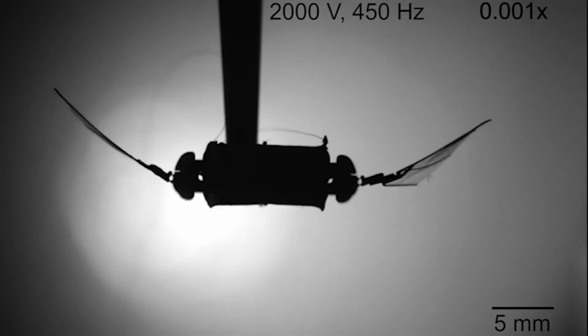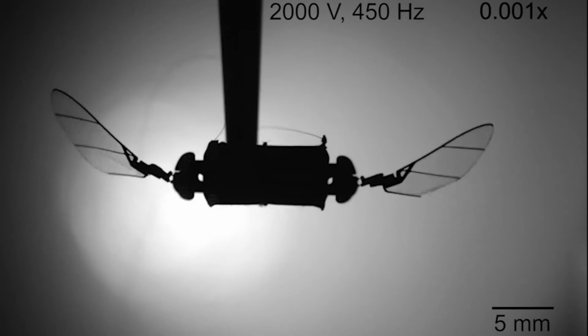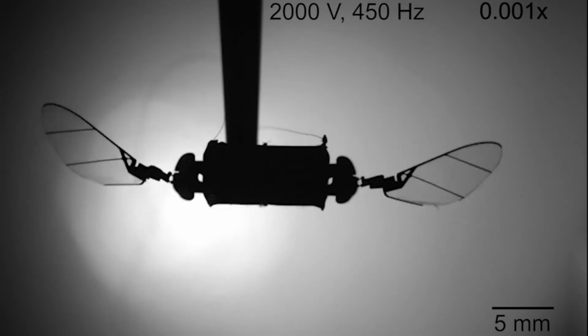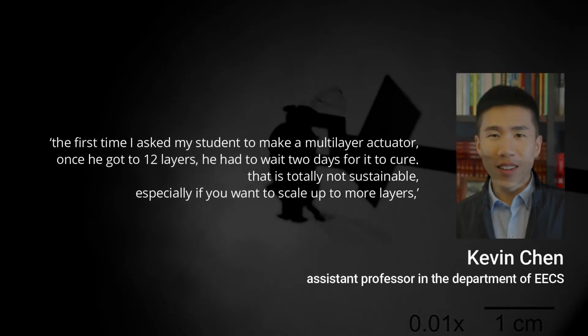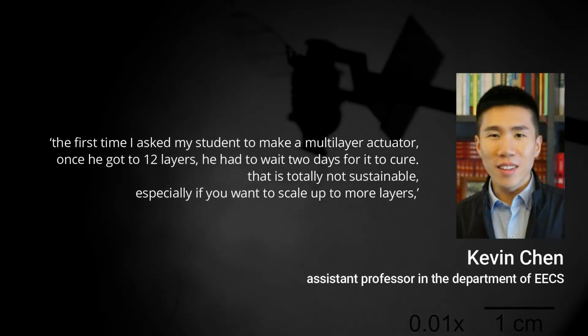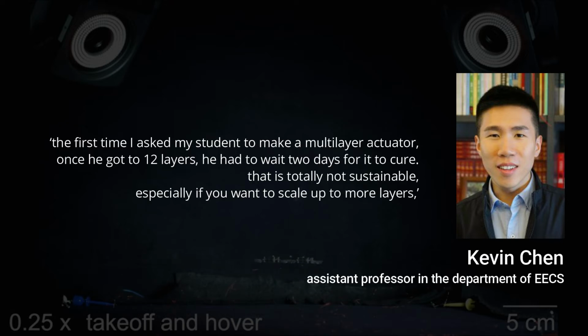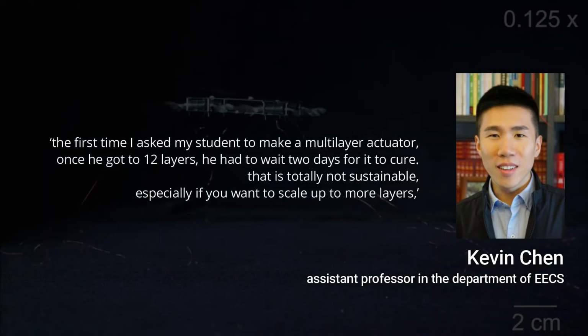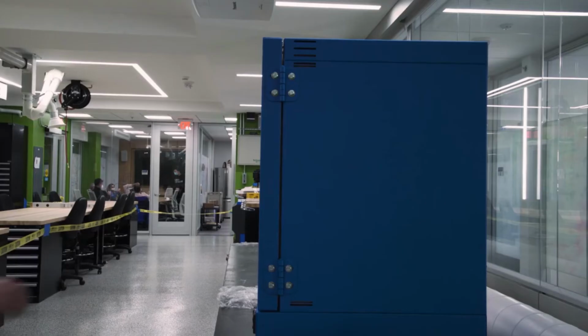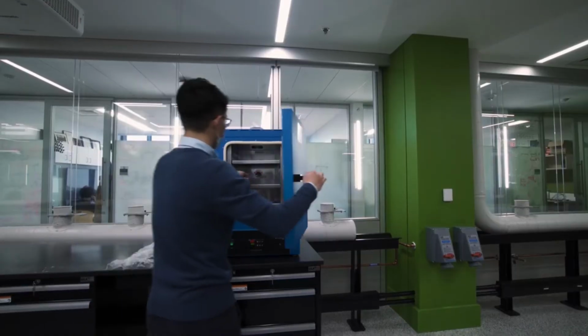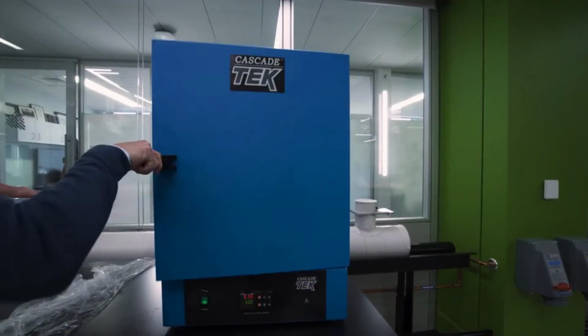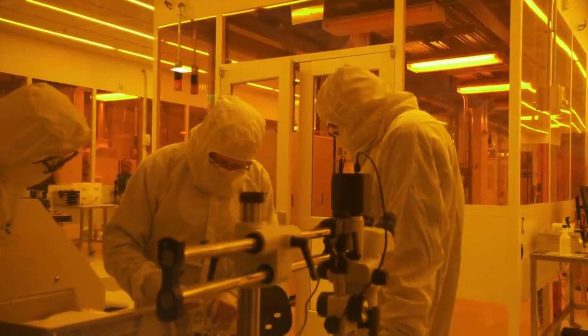Another difficulty they had to deal with was that as more layers were added, the actuator took longer and longer to draw. The first time I asked my student to make a multi-layer actuator, once he got to 12 layers, he had to wait 2 days for it to cure. That is totally not sustainable, especially if you want to scale up to more layers. They discovered that baking each layer for a few minutes immediately after the carbon nanotubes are transferred to the elastomer shortens the curing time as more layers are added.